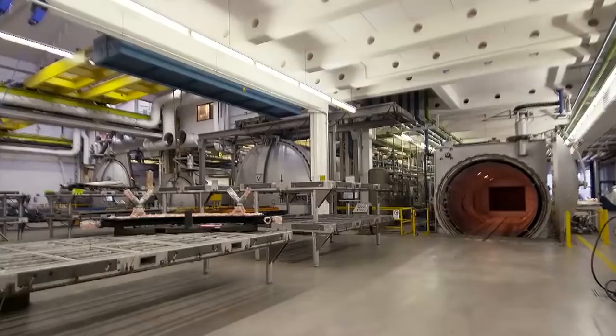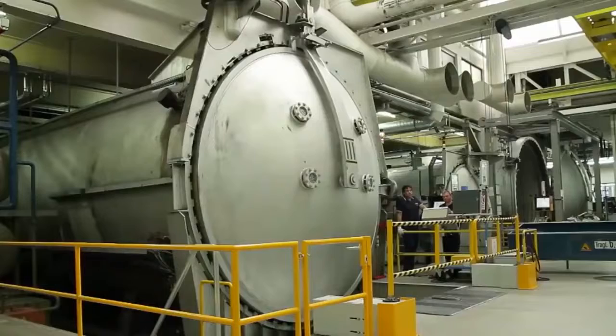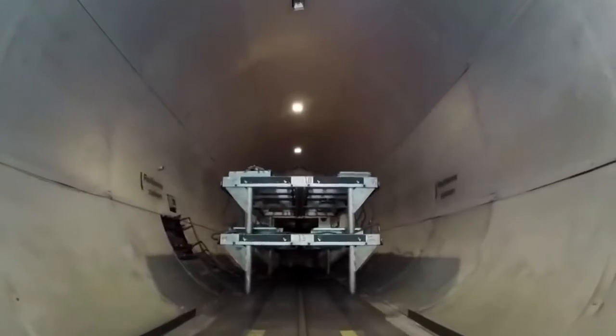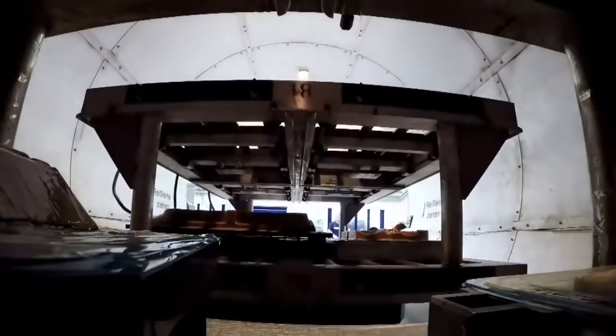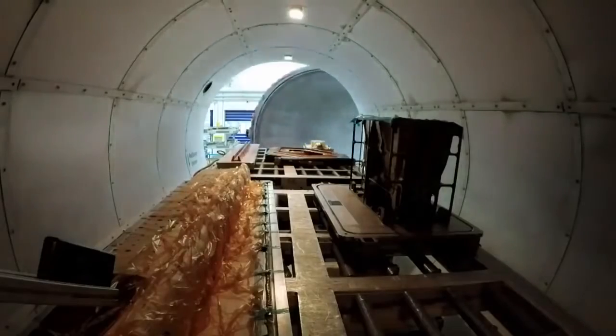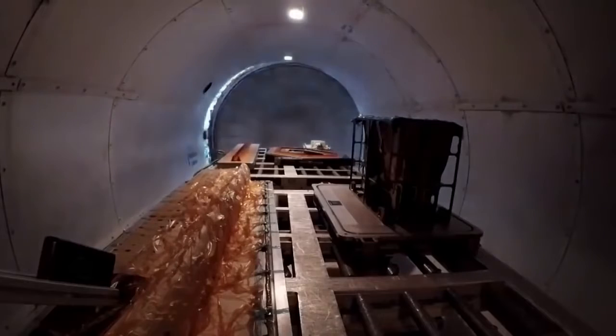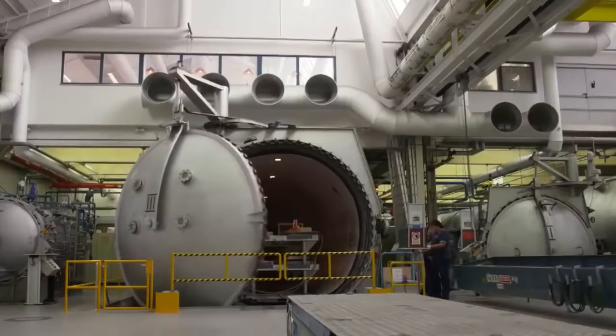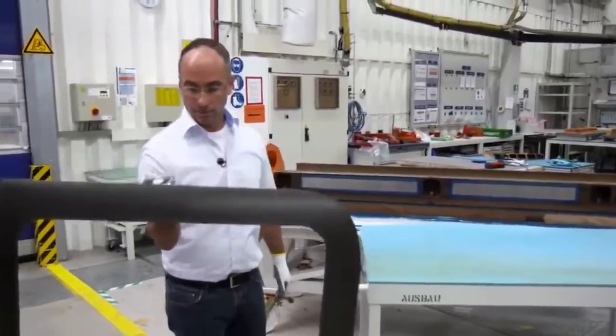In the autoclave, the composite parts are subject to heat and pressure. A standard home pressure cooker works on the same principle as this autoclave. Inside the autoclave there is a pressure of 7 bar and a temperature of around 180 degrees Celsius. The side doors and other frame parts are subjected to these conditions for 10 hours. When finished, it is so light that you can pick up the side door with one finger.